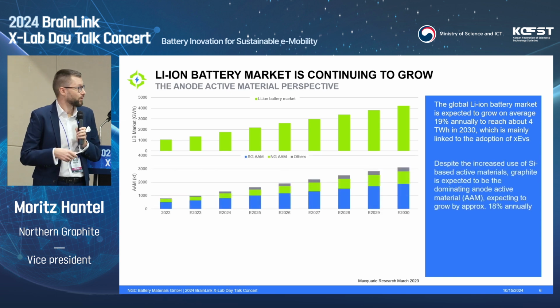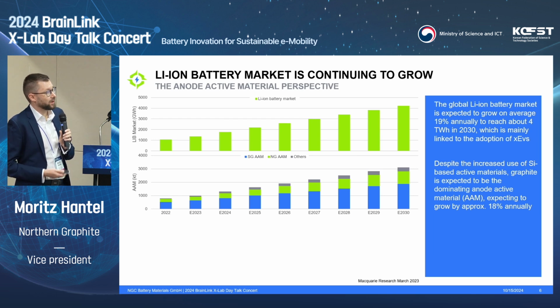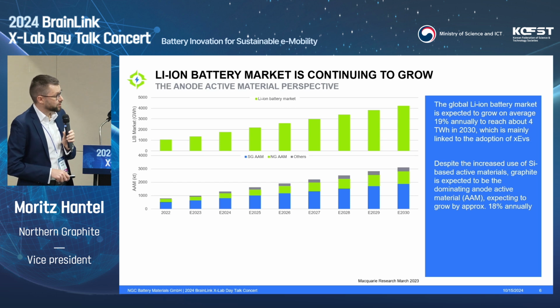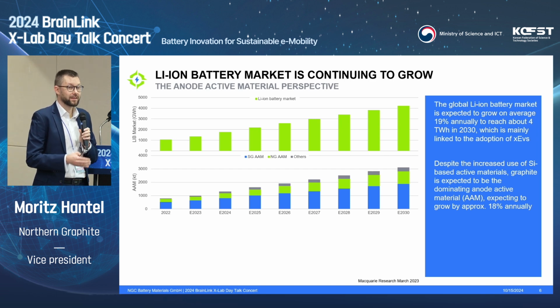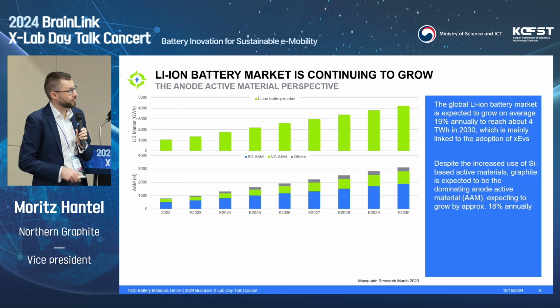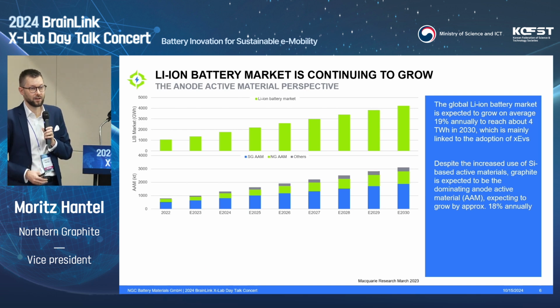Looking now from a carbon perspective, so AAM, anode active material, so carbon, even though we talk about silicon anodes, typically a silicon anode is 5 to 10% silicon and the rest is still graphite. So graphite is still the dominating factor on the anode side. And what we measure here is the amount of anode active material required to power these kinds of batteries. We're talking thousands of 1,000 tons, so KT, kilotons, and at the end of the decade around 3,000 kilotons of refined anode active material is required to power these batteries.